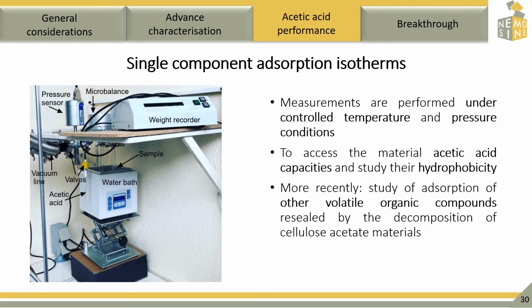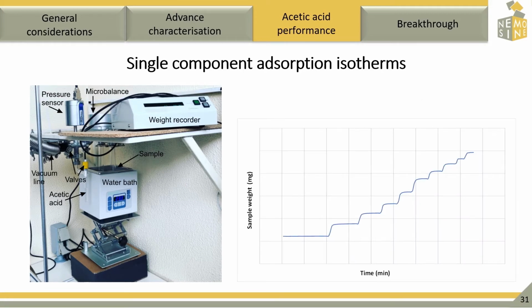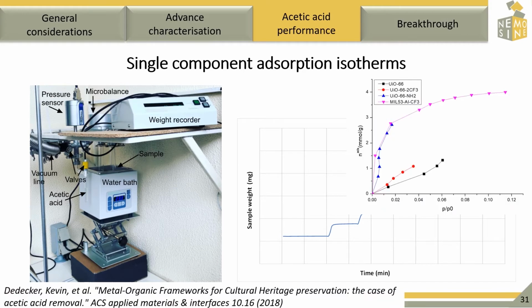Also in this setup, we can now do isotherms with different volatile organic compounds, such as acetone, acetaldehyde, methanol. By evaporating the vapor, we can control the mass increase over time and quantify how much acetic acid and water the material can adsorb at a given relative pressure. Comparing this way the hydrophobicity of the material with their affinity to capture acetic acid. Here, we can see typical acetic acid isotherms obtained with this setup for different MOFs, and it's possible to see that the acetic acid adsorbed depends on the material tested.